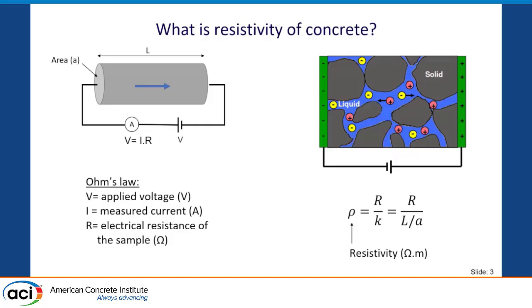For a cylinder where you apply the current through the two ends, the geometry factor is the length divided by the cross-sectional area. If you have a different configuration of electrodes, the geometry factors may be more complex, but it's a number that can be measured experimentally or calculated numerically, and essentially it's a constant. That's what matters. So you get that resistance, you divide it by the geometry factor, and you get your resistivity.